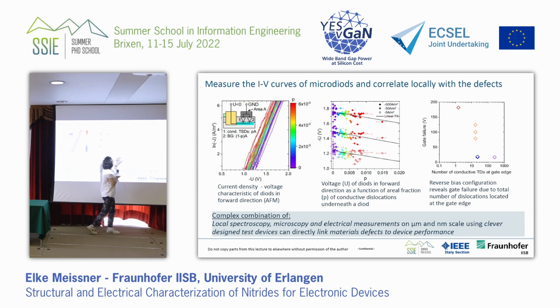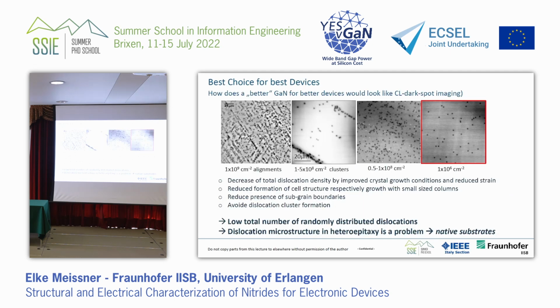And finally, if we make the model for this, we can associate the gate failure to the number of conductive threading dislocations at the gate edge. And this reveals clearly that the total number of conductive dislocations, which is located close to the edge, is in that case determining the early breakdown of the device. And this was the first time that we were successful really showing the full chain from the material at the very beginning until the final device, and we directly could correlate it to the performance of the device.